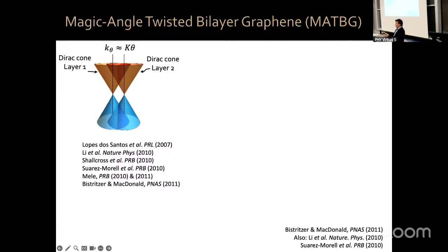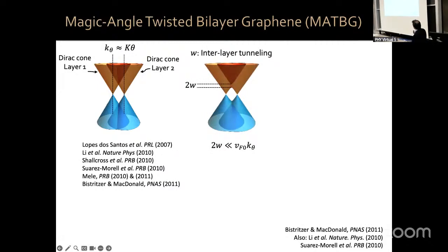But when we place graphene on top of graphene to make twisted bilayer graphene, the two graphene sheets are spaced by just a few angstroms. Electrons are very much aware that the other graphene sheet exists, and particularly they can tunnel between the two sheets. That interlayer tunneling gives rise to an energy repulsion at the crossing points - band repulsion.